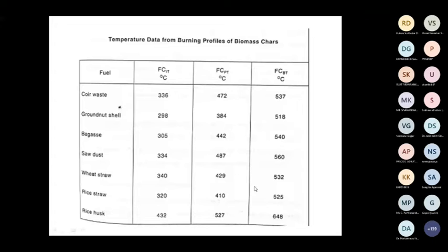Here you can see some useful information. Among all the fuels, rice has the highest burnout temperature, 648, whereas the others are 537, 518, 540, 560. This very clearly indicates that rice combustion is relatively very difficult. Complete combustion of rice will be difficult compared to all the other fuels because of 648 degrees. This is one of the important conclusions you can draw. Based on the burnout temperature, you can tell which fuel can be burned completely more easily. You can see groundnut shell is very easy, close to even 518, followed by coir waste. Among the fuels, sawdust and rice are the highest, very difficult.